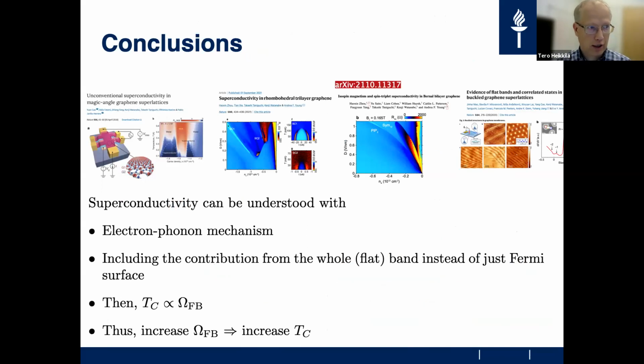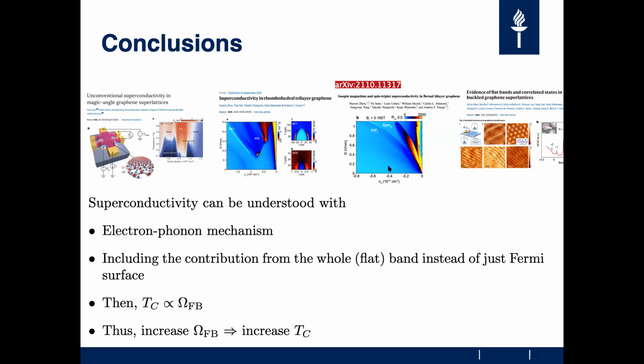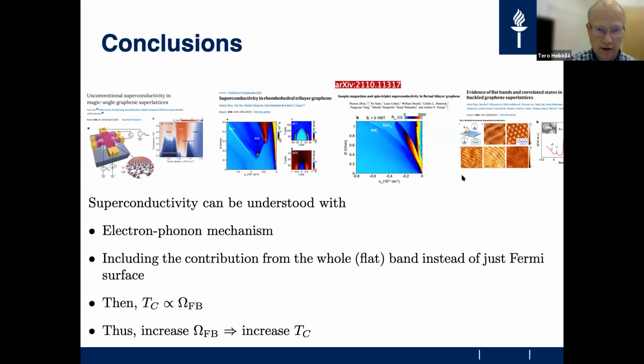What I am now claiming is that there are now several experiments on superconductivity in graphene-based systems: twisted bilayer graphene, rhombohedral three-layer graphene, Bernal bilayer graphene. There are also some experiments on strained graphene. And my claim is that superconductivity in all these systems can be understood with the electron-phonon mechanism.